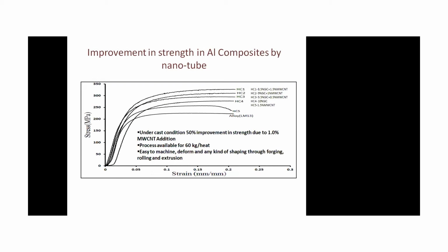Of course, we are adding some ceramic into the aluminum matrix, but instead of only one ceramic element, if we add another ceramic element like CNT or graphene along with it in the aluminum matrix, like in this case, we are adding silicon carbide as well as CNT into the aluminum matrix, we can see that if only silicon carbide is there, then strength is not so much. But when we add both, then strength is much higher than the conventional, because one is causing the primary hardening, another causing secondary hardening of the system. So that will create some kind of stress field that increases your strength. So that is also one of the works we are doing.